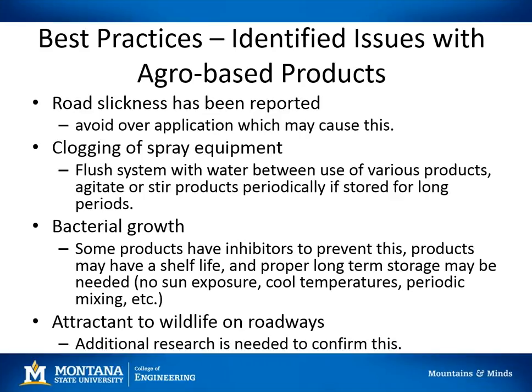But proper long-term storage for excess material would be no sun exposure to avoid that helping bacterial growth, cool temperatures, so in the shade or inside, and then with periodic mixing. And then anecdotal evidence has suggested that these products may attract wildlife to the roads, but we already know that salts alone attract wildlife, and there's no research yet that shows that ag-based products added to salt attract more wildlife. We definitely recommend additional research in this area, but at this point in time, there's not enough information to conclusively say one way or the other.